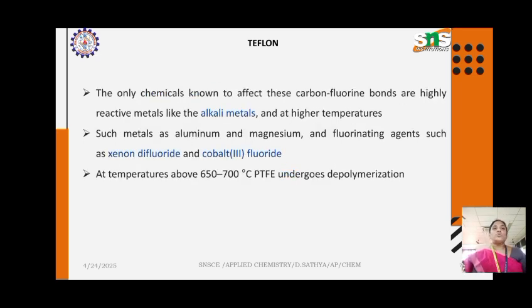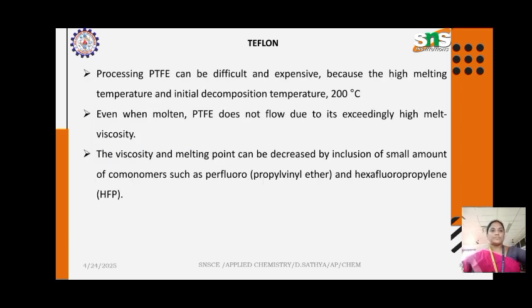The only chemicals known to affect the carbon-fluorine bonds are highly reactive metals like alkali metals, which we discussed in the previous slide, at high temperature. Such metals include aluminum and magnesium, and fluorinating agents like xenon difluoride and cobalt(III) fluoride. At temperatures above 650 to 700 degrees Celsius, PTFE undergoes depolymerization. The processing of Teflon can be difficult and very expensive because of its high melting temperature, so the production is very tough.